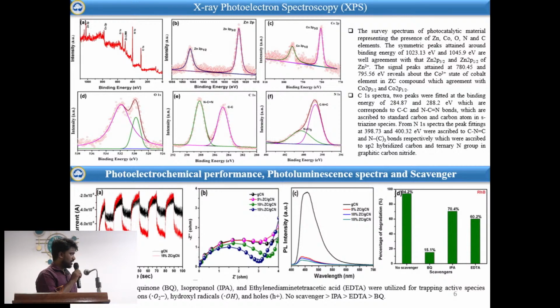And in the PL studies, figure C shows the recombination rate of the particular sample. The higher the intensity, the higher the recombination rate, that's the principle. So with respect to the composite sample, we obtain a minimum intensity, which implies there is not much recombination of electrons to the valence band. So it has been retarded, and many electrons have reacted at the surface of the material, at the surface of the pollutant for the degradation process.